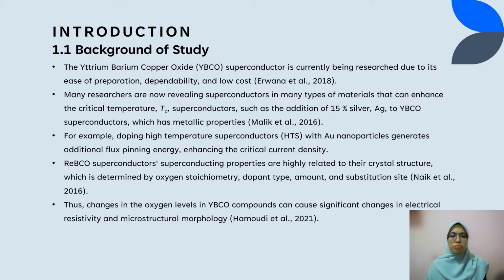The YBCO superconductor is currently being researched due to its ease of preparation, dependability, and low cost. Many researchers are now revealing superconductors in many types of material that can enhance the critical temperature of the superconductor, such as the addition of 15% silver, Ag, to YBCO superconductor, which has metallic properties. For example, doping high temperature superconductor with Au nanoparticles generates additional flux pinning energy and enhances the critical current density.